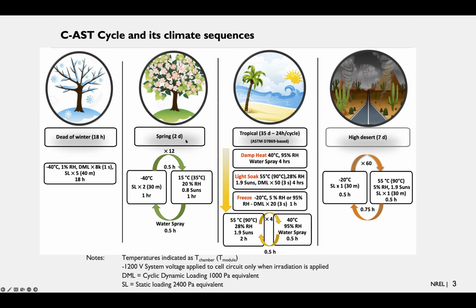There's a spring cycle, and this is essentially to replicate freeze-thaw. The maximum temperature of the air in the chamber is 15 degrees C, and the maximum temperature of the module is 35 degrees here. So it's relatively modest levels of temperature that we see. And there's water spray again to achieve the freeze-thaw cycles that you might see.